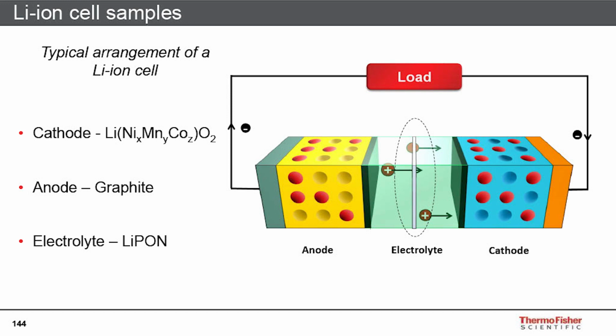But it is looking at lithium-ion batteries. And so we have our anode material, which at the moment typically is graphite, our cathode, which is usually some kind of oxide that's able to intercalate the lithium ions, and then electrolytes. We could be certainly now looking at moving from liquid electrolytes, this is exceptionally good news for XPS because we don't really like the fluorinated liquids that they use for electrolytes at the moment, but moving to solid state ones like Lipon is much better for XPS analysis. And also if you've got solid state lithium-ion batteries, you can put much more energy into them. So the energy density and hopefully then the range of your car will be a lot larger if you've got a solid-state battery rather than one with a liquid cell.